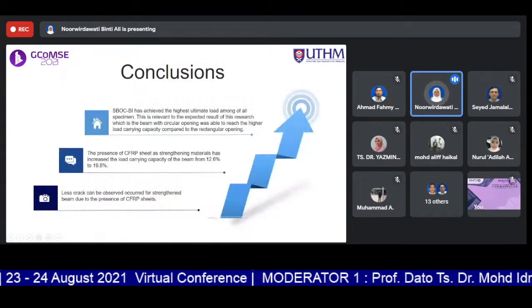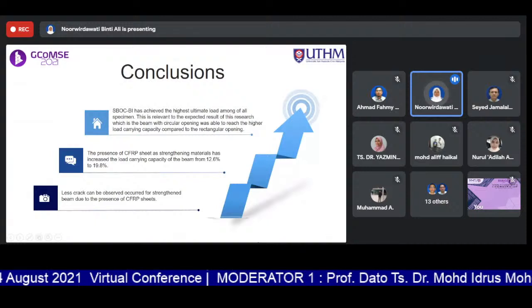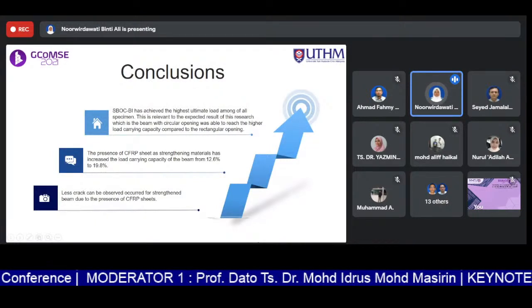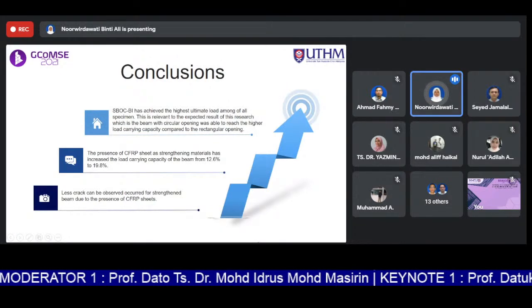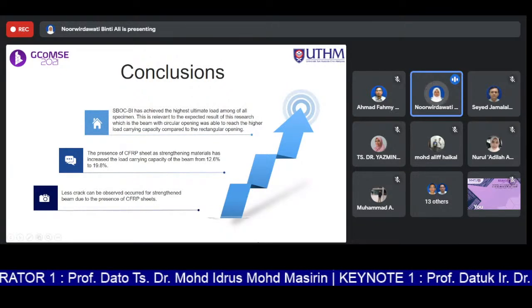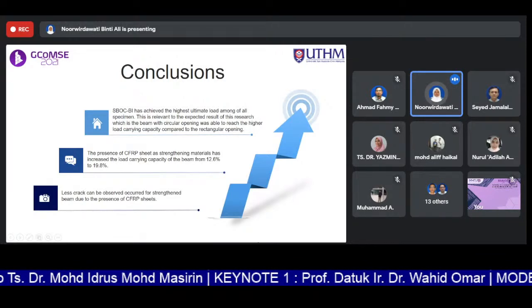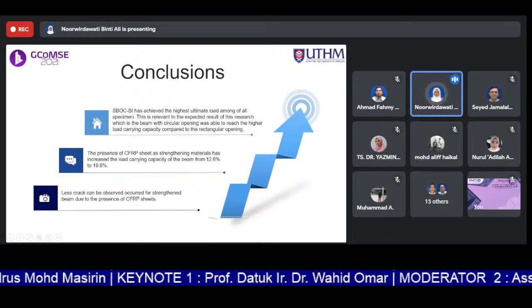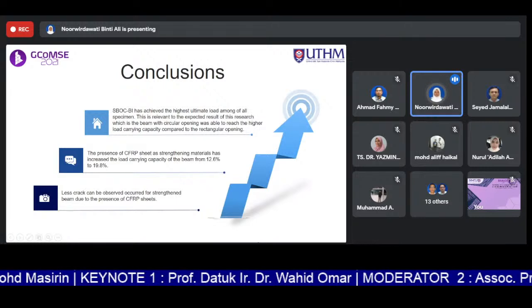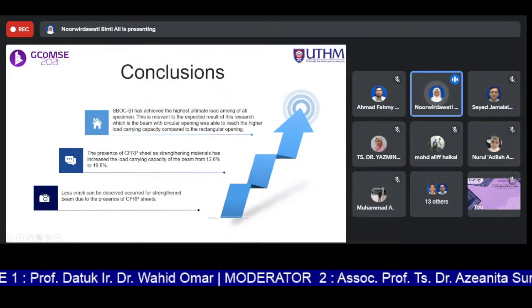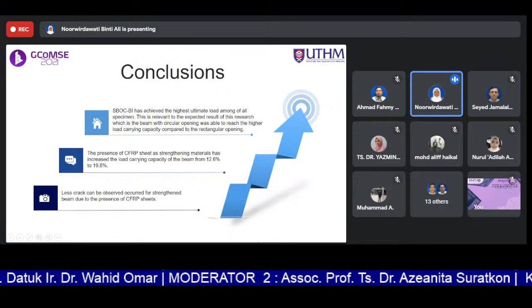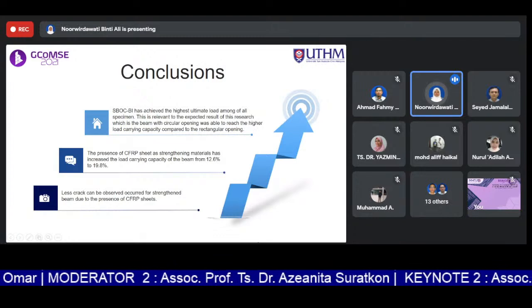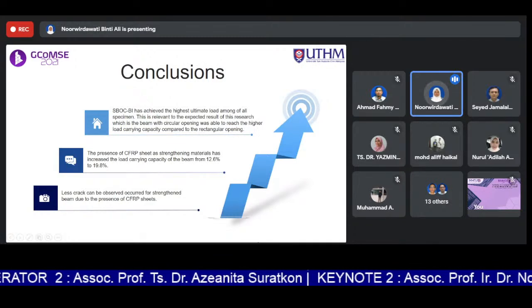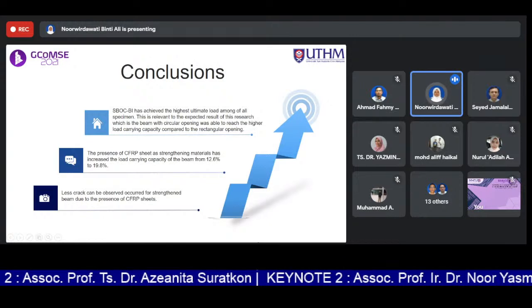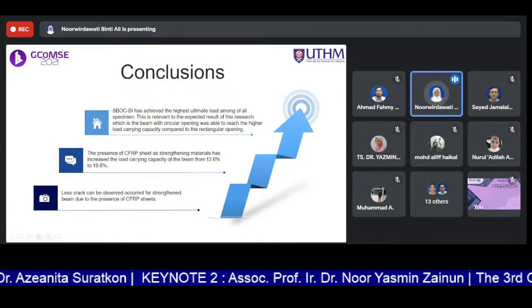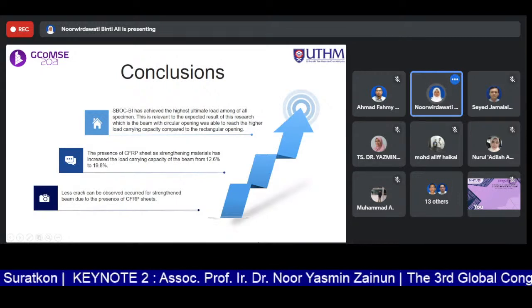So as for the conclusion, SBOC-BI, the beam with circular opening that we strengthened, has achieved the highest ultimate load among all specimens, and this is relevant to the expected result of this research, which is that the beam with circular opening was able to reach higher load carrying capacity compared with the rectangular opening. If we compare between the two types of opening, circular and rectangular, the rectangular opening will achieve lower load because of the four edges.